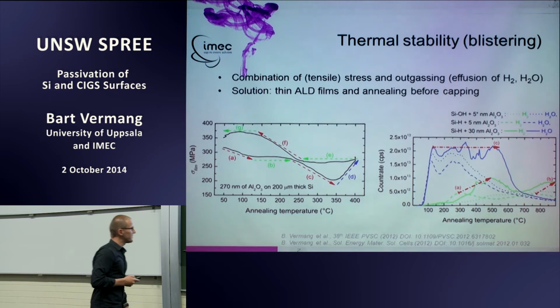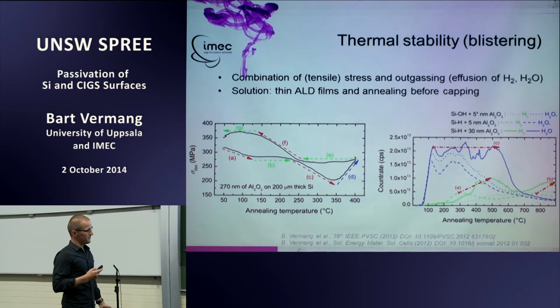On the right side, you have outgassing, where we used a mass spectrometer to measure a few gases coming out of the aluminum oxide layer during annealing. And there you see water and H2 for different thicknesses, 5 nanometer or 30 nanometer, and different cleanings. So hydrophobic or hydrophilic cleaning before you grow the aluminum oxide layer. But more importantly, what you see is that a lot of hydrogen in the form of water or H2 is coming out of your aluminum oxide layer. And it stops at the moment you make blisters. So these two are related to the formation of blisters.